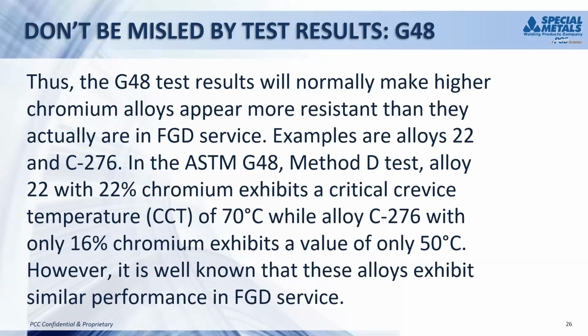Typically, the media inside an FGD system will be reducing. So the oxidizing nature of the ferric chloride is somewhat different. In general, materials with higher chromium provide better corrosion resistance to oxidizing salts and acids. So the alloy 22 with 22% chromium does indeed provide better resistance in this test, with a higher critical crevice temperature in degrees C compared to alloy C276. But the two behave in a very similar manner in FGD environments. So obviously you would be misled if you tried to use these results to compare these two materials.